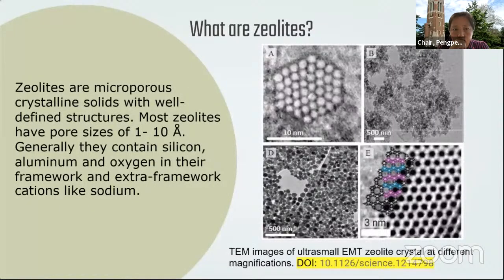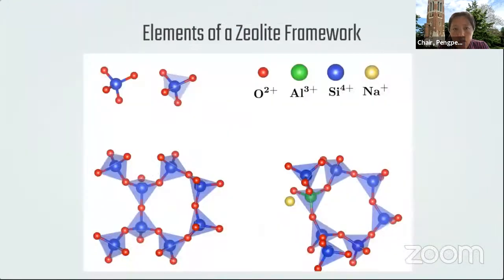Zeolites are microporous crystalline solids with well-defined structure. Most zeolites have a pore size of 1 to 10 angstrom. Generally, they contain silicon, aluminum, and oxygen in the framework and extra-framework cations like sodium. The most basic element, no matter which zeolite we refer to, is the tetrahedral structure. It commonly consists of silicon atoms surrounded by 4 oxygen atoms. The oxygen bridge can join these to other tetrahedra to give rise to different crystalline structures.